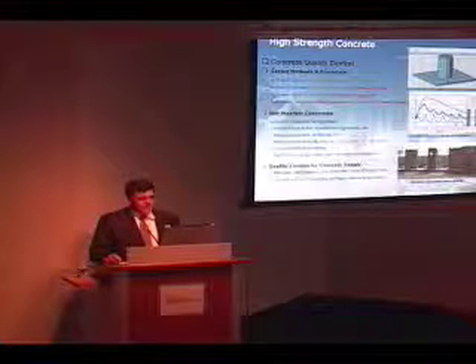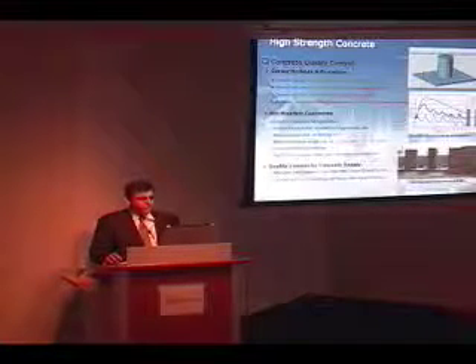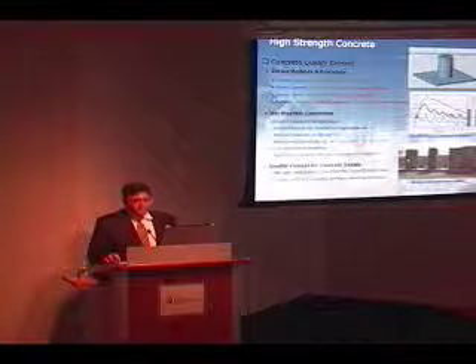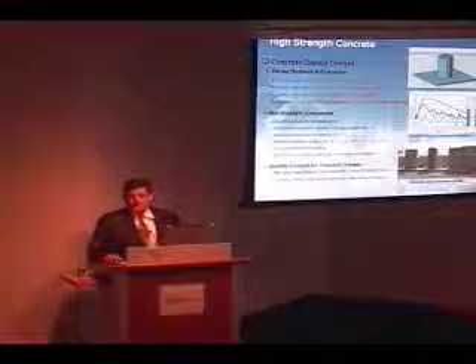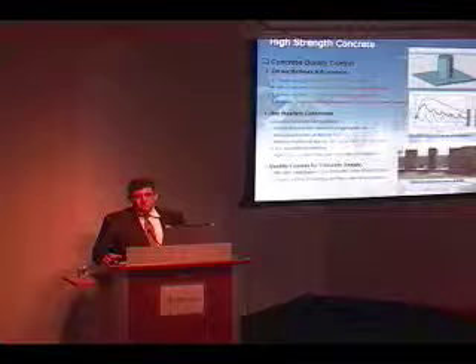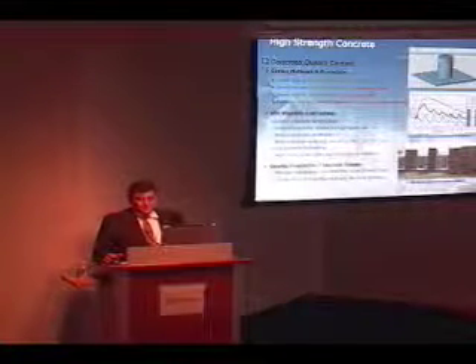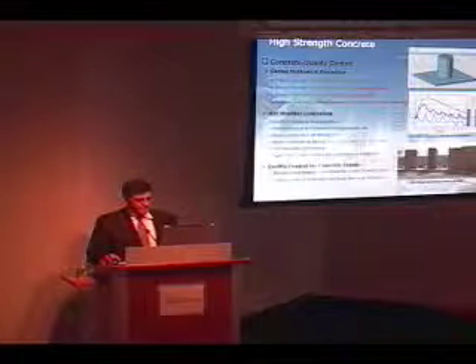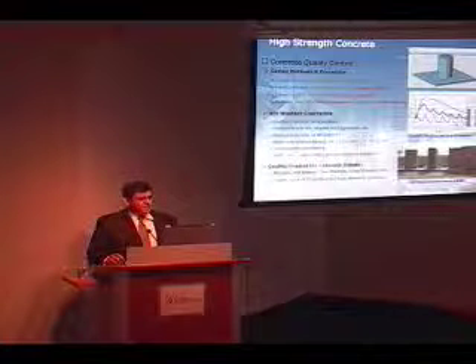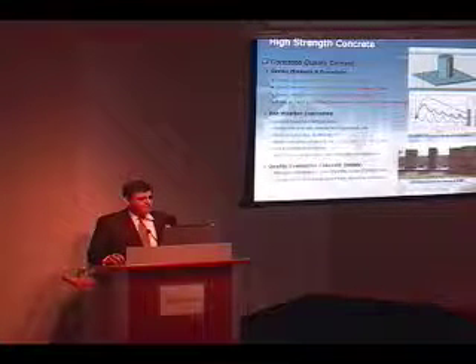So what you see here is the curing methods. We also tested what type of curing method to use. So we investigated all types of curing methods for proper curing for both vertical and horizontal members, for the walls, for the columns, for everything that we could think of, just to make sure that there is no cracking that happened in the concrete during construction, which in many projects that you will see, even in the States, is very difficult to control sometimes. And mass concrete, we have very large elements in which we did a lot of testing for that.